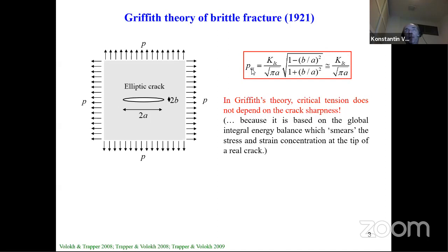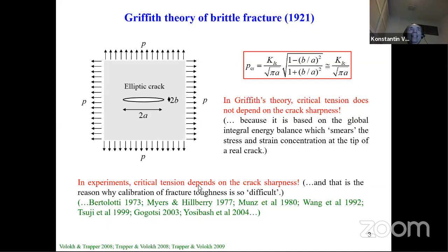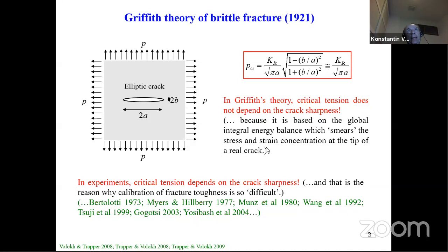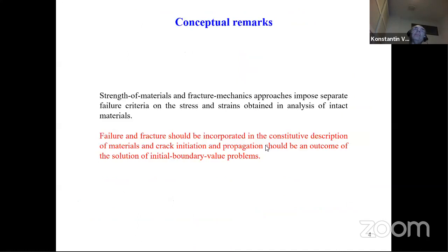But when people do experiments, critical tension depends significantly on the crack sharpness. This explains why the calibration of fracture toughness is so difficult — I would say it is impossible — because your result depends on what crack tip you have in your experiments. Nevertheless, it was the first work in the direction of fracture mechanics, and it is important that cracks were explicitly considered in this paper.